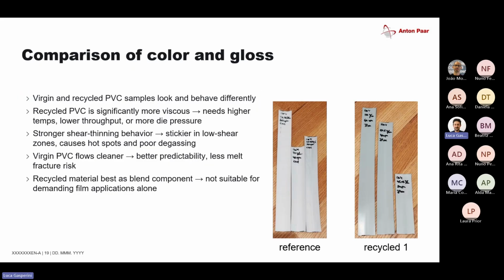Another effect you see, especially with PVC, is that once you change something within the process, it's very likely that the color will also change. If you're getting too hot, you start to burn your PVC material. If you have some additives, that might also have an effect on the optical properties of the ribbon. These are, for example, samples extracted from a viscosity measurement. You get these small ribbons, and you could see that the PVC samples which contained the recycled material had a much darker color shade. Depending on your application, this could affect it quite a bit. If it's visible anywhere, you don't want to have the discoloration, so it's not really suitable for demanding film applications.